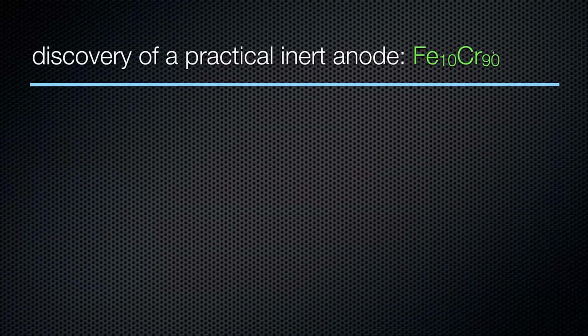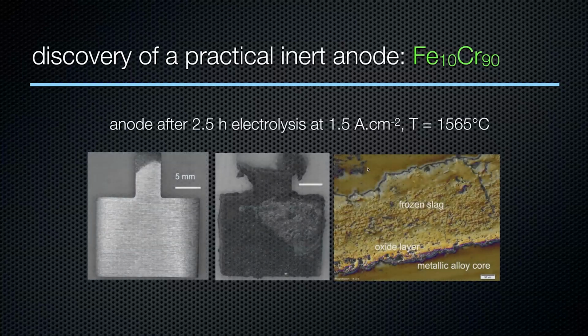And the practical inert anode was an alloy of chromium, 90% chromium, 10% iron. And this forms a surface film that's protective. I'll show you some images. This is some early work that we did. In the left frame here, you see the machined anode before it's immersed in the electrolyte. And then this is after 2.5 hours at 1565 degrees Celsius. The reason it looks so ugly is that it's covered with drag out of the electrolyte. The actual anode was in pretty much pristine condition.